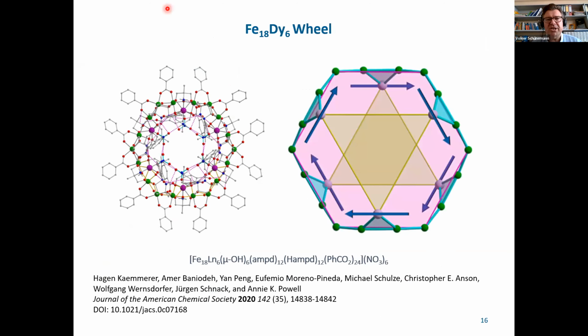We also could measure another system, very beautiful, an iron dysprosium wheel. So here you see the dysprosium ions, dysprosium 3 ions, and the iron around here. Basically, they follow the magnetization of the dysprosium. And the ground state of this dysprosium wheel is diamagnetic, but a toroidal state. And these states are very interesting because you can switch the direction of the dysprosium magnetization by applying electrical fields. Therefore, toroidal systems are also quite interesting.